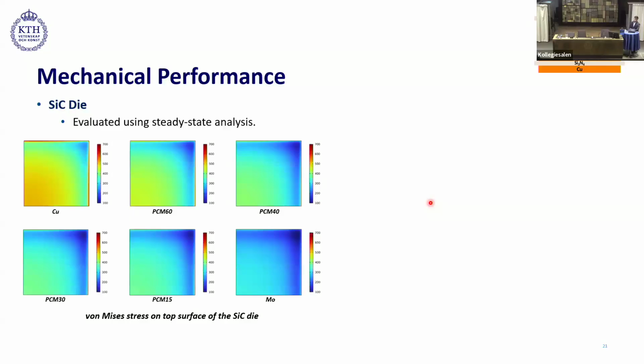Coming to the mechanical performance of these packages, first we will start with silicon carbide die. This was evaluated using steady state analysis, and we used von Mises stress as a performance criteria. So what we see here is von Mises stress on top surface of the die, and we observed that von Mises stress is higher when the copper percentage in the spacer composite is also higher, and it reduces with decrease in percentage of copper. Therefore, in case of molybdenum, we see minimum von Mises stress on the die.